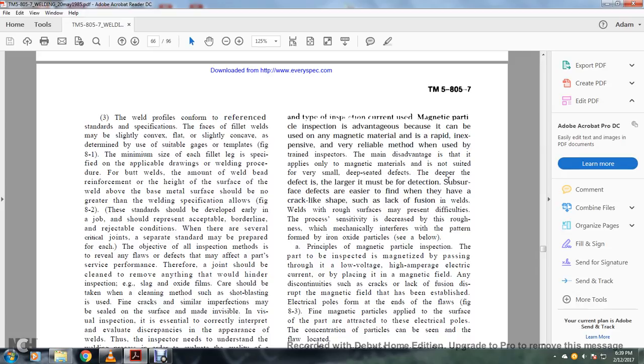Subsurface defects are easier to find if they have a crack-like shape, such as lack of fusion in welds. Welds with rough surfaces may represent difficulties. Process sensitivity is decreased with roughness, which mechanically interferes with the pattern formed by the iron oxide particles.